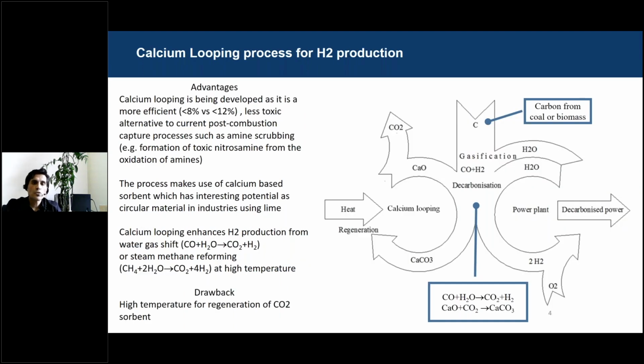For CO2 capture, absorption is the industrial standard option due to the proven applicability with solvents like monoethanolamine. But unfortunately, this chemical seems to suffer from the presence of oxygen. In fact, in presence of oxygen, amine can form a toxic compound like nitrosamine. So calcium looping seems to be an environmentally benign alternative to the absorption stripping process.